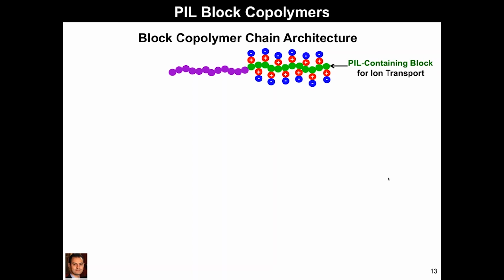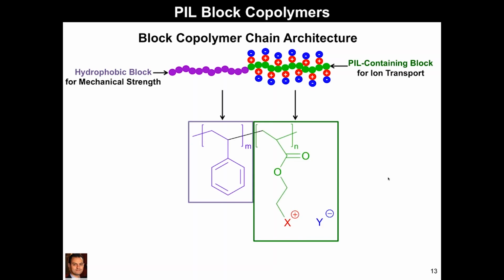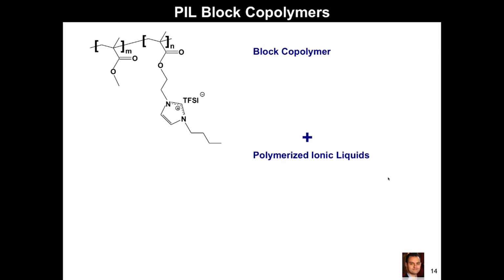So one of the blocks of your block copolymer could be a polymerized ionic liquid containing block, and you can grow that chain, let's say after or before you would grow a typical commodity plastic like PMMA or polystyrene. And here just shows you an example structure of polystyrene and then our PMMA-based polymerized ionic liquid, where again we have a covalently attached cation. And the rationale for doing something like this would be to combine properties that you would see of the block copolymer and the polymerized ionic liquid.